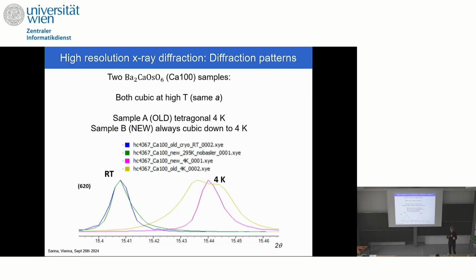Nominally, they are the same. Both of them are cubic at high temperature with the same lattice parameter. You can see here this peak, which is the 620 Bragg peak, for both the samples at room temperature is at the same position. They have the same lattice parameter, the same structure.